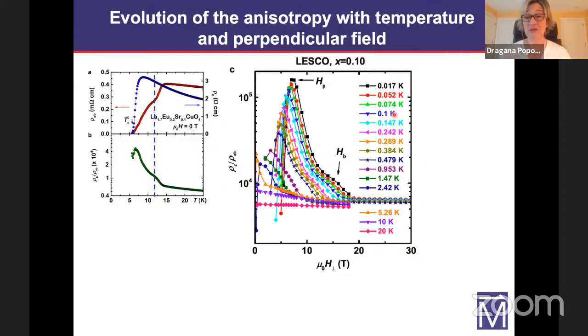However, as you reduce the temperature, we start seeing this very non-monotonic behavior. For example, let us focus on the lowest temperature, 17 millikelvin. These are the black symbols. So as we increase the perpendicular field, the anisotropy ratio increases by more than an order of magnitude. So clearly the planes are getting decoupled by the magnetic field. As we increase the field further, the anisotropy drops. We are left with fluctuating superconductivity in the planes.